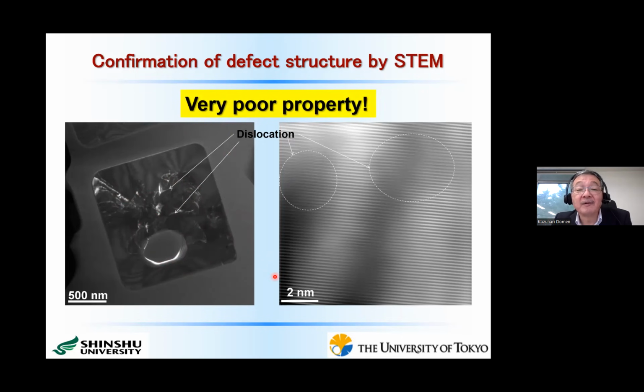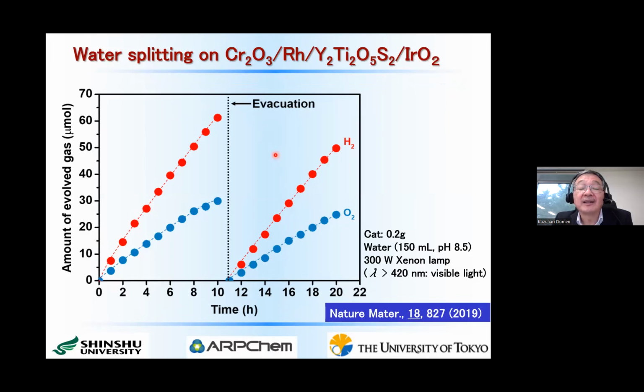But however, when we modify our photocatalyst, again by rhodium and chromium mixed oxide core shell structure, and in this particular case, we used iridium oxide nanoparticles as an oxygen evolution co-catalyst, which was adsorbed from the iridium oxide nanocolloid solution. Then when we irradiated by visible light, you see that both hydrogen and oxygen evolution takes place in a 2:1 ratio. This is the first example of the overall water splitting reaction based on oxysulfide materials.